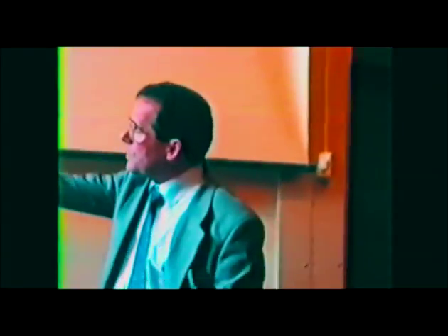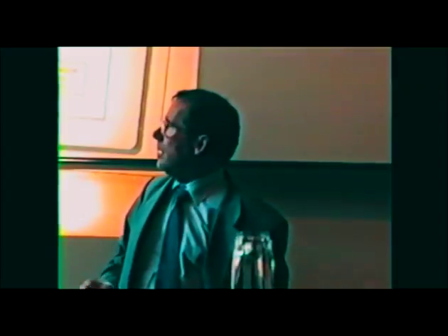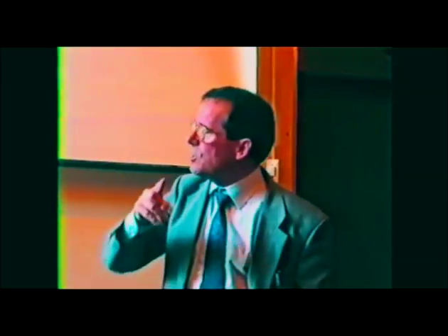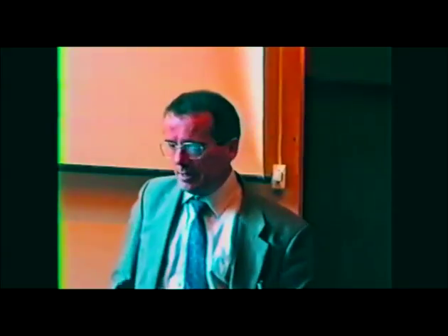First point to make is that this condensation step is a strong function of pore width, so the shape of the molecular isotherms, these isotherms from individual pores, are strong functions of pore width. So it's possible to relate these isotherms to pore width. The second point, which is interesting in relation to Roger's work, is that if you were to write the condensation approximation on this isotherm, it would be like that. So the condensation approximation could be regarded as a crude approximation to the sort of isotherm that's been derived here.